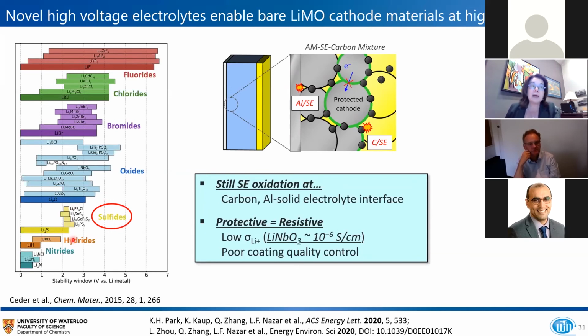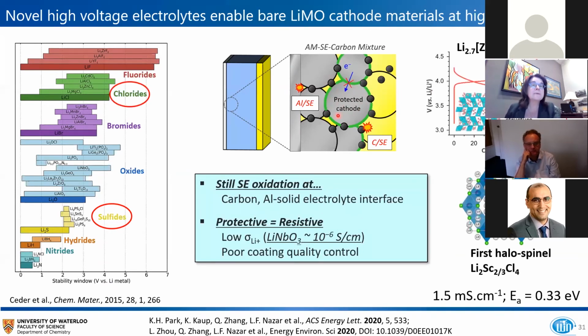What is better are the chlorides. And computation by Gerbrand Ceder's group shows that they have oxidation potentials upwards of 4 volts, which makes them compatible with these lithium metal oxides. So recently we've developed 2 such materials that have high ionic conductivity. It's not as high as the argyrodite I mentioned, but it's sufficient. It's above that benchmark of 1 millisiemens with attendant reasonably low activation energies.